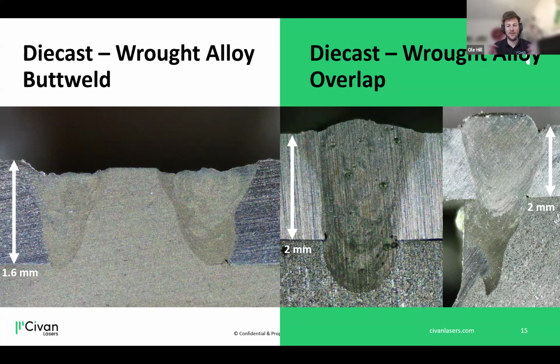Let's say you now only have 50% of the dangerous material of die-cast, and you have 50% of easier-to-weld wrought alloy. As you see on the left, there's basically zero porosity inside this weld. And on the right, you can see overlap of wrought alloy over die-cast. That seems to be the most challenging weld, but we have a way of getting a nice wide interface as well. It's important to note that clamping is an important task when you weld overlap. I think that's regardless of whether you're using a Civan laser or not. If you want to weld successfully in overlap, you need a good jig.